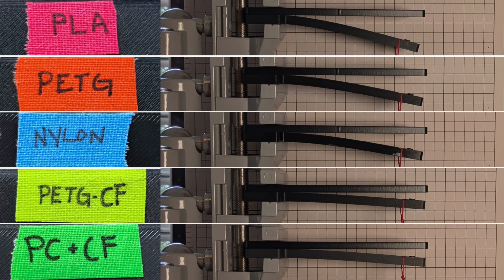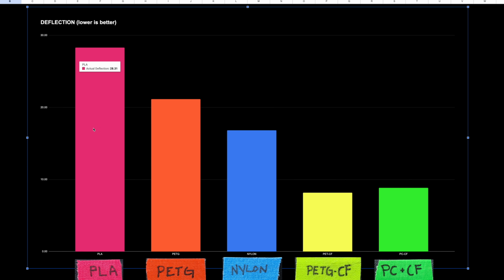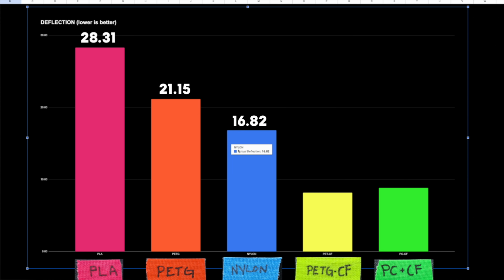So that's what you're seeing in this graph. PLA is coming in last. It deflected a whole 28 millimeters, followed closely by PETG at 21 millimeters. Nylon came in third at 16.82, and then there's two standouts here towards the right, with PET-CF coming in at 8.15 millimeters, and then the polycarbonate carbon fiber blend coming in at 8.85.